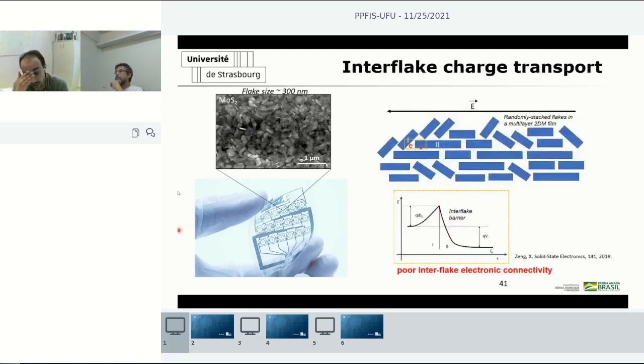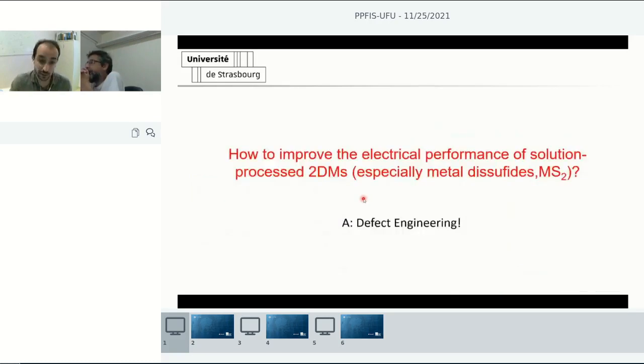And when you pile up several flakes like this, the charge transfer becomes compromised, because there will always be an energy barrier between two adjacent flakes, meaning that to transport current along these films, the electron will always face an energy barrier. So there is poor interflake electron connectivity for this kind of sample.